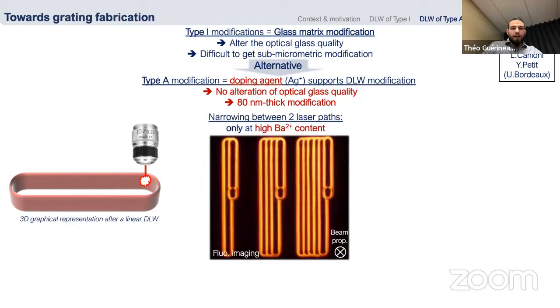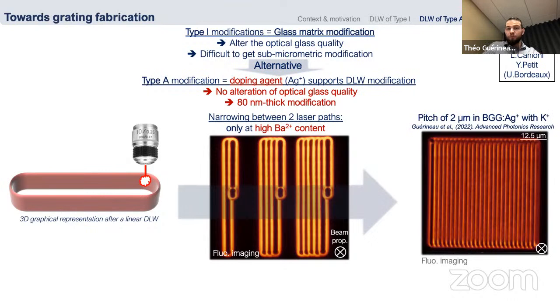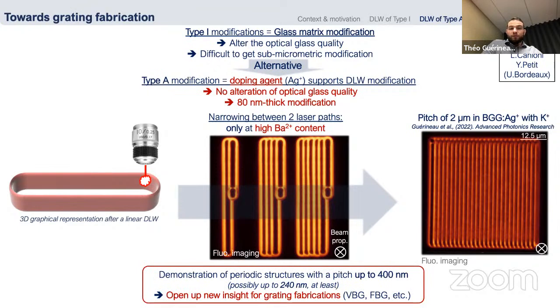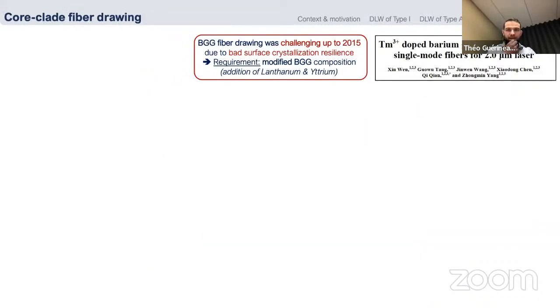By narrowing 2 laser paths, which we can do for now only in a high concentration of barium, we can artificially decrease the distance between 2 walls. Here you have the picture for a structure with a pitch of about 2 micron. And we demonstrated a structure with a pitch down to 400 nanometer, and for some glass compositions down to 240 nanometer. That's very interesting because it opens up a new insight for the fabrication of gratings.